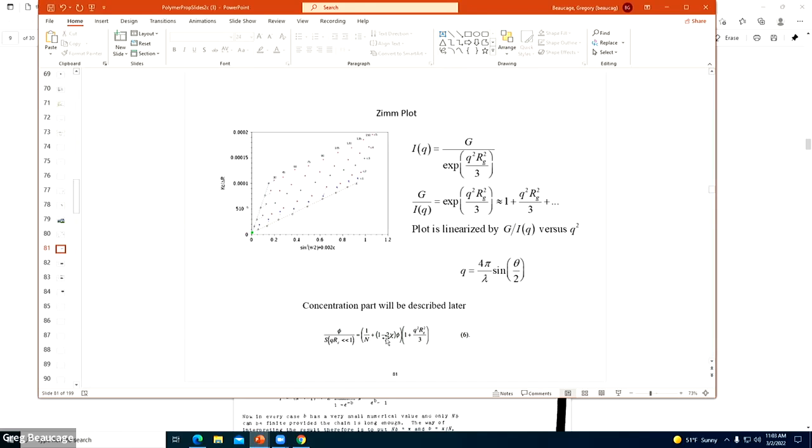And so it's a colligative property you're measuring. And then this gives you, actually, it doesn't give you the number average. It gives you the weight average, because it ends up being the weight average. Sorry about that. This gives you the weight average. The osmosis thing gives you the number average. And then this gives you the chi if you get the slope and concentration.